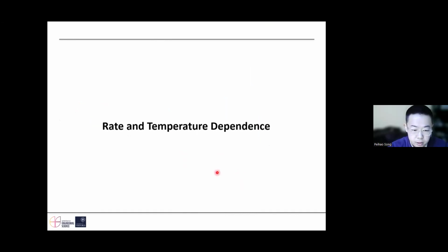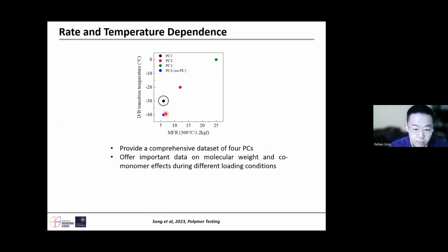After performing the tensile test, I performed the melt flow rate and temperature dependent test. Here, the tensile test was based on this material. We received the other materials from our industrial partner. So here is a different molecular weight polycarbonate. The melt flow rate means different molecule. They changed that to change the ductile brittle transition.